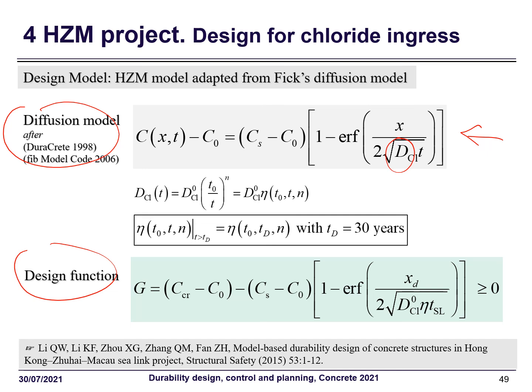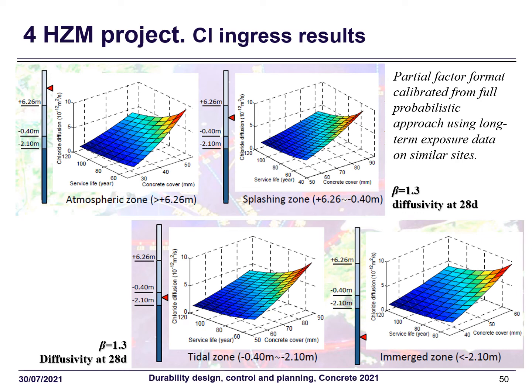The first is we have to take into account the statistical property of all these parameters. In this way, only in this way, we can have some design margin. And the second thing is these parameters are all environment dependent. So we have to calibrate this model on the local data. So fortunately, we have long-term exposure data on similar sites available to us, and using this data we calibrate the partial factor design equations from the full probabilistic format, and here are the results.